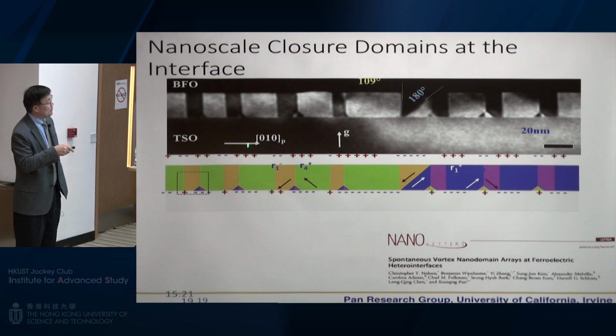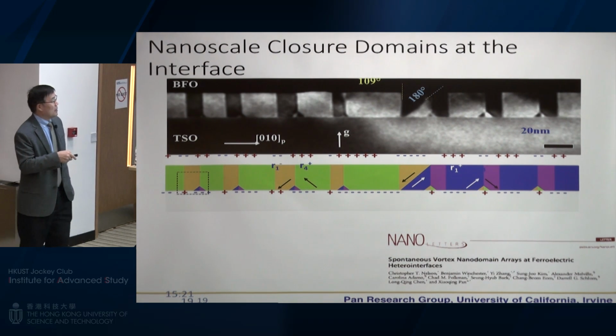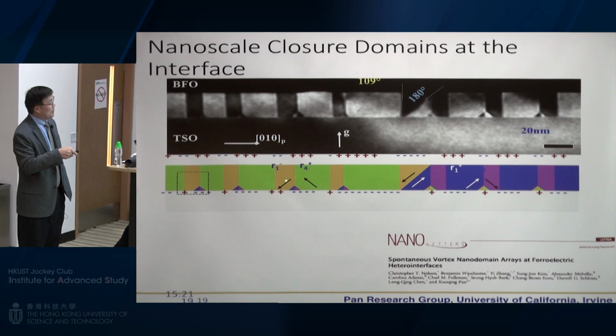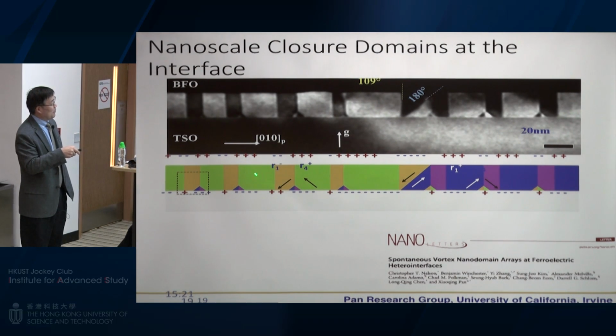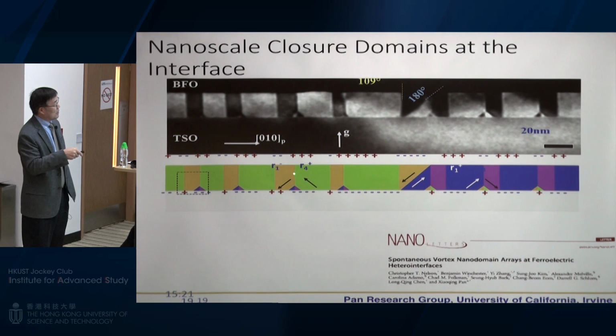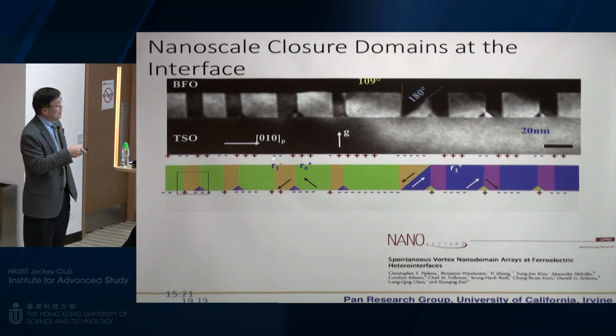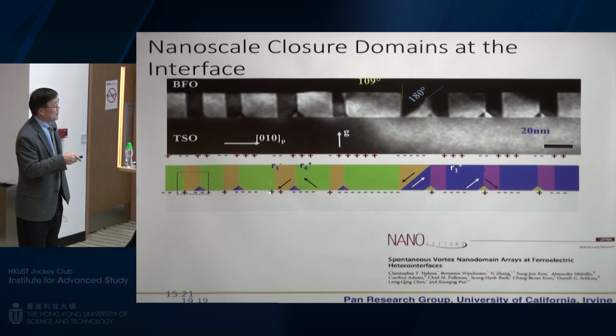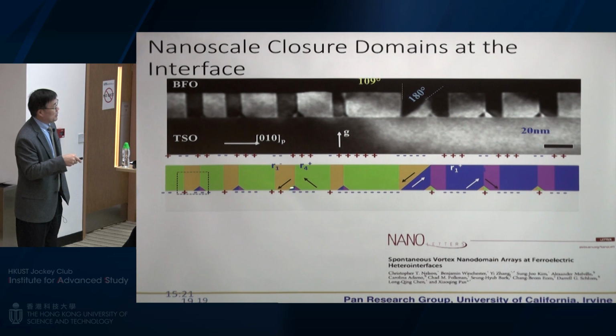So this is a vertical ferroelectric domain. In this type of domain, the polarization goes in this direction. In the next domain, the polarization goes in the other direction. So the rotation is 90 degrees in the plane, but in three-dimensional space, this rotation is 109 degrees. Okay? So from here to here is back to the same polarization state as that one. So technically, this domain wall and that domain wall should be equivalent. Okay? But at the termination point, the characteristic will be different.